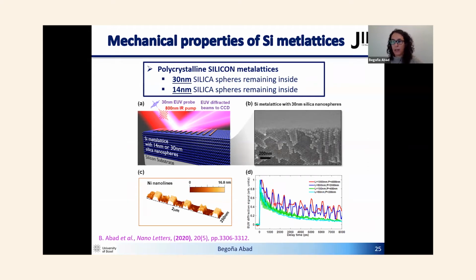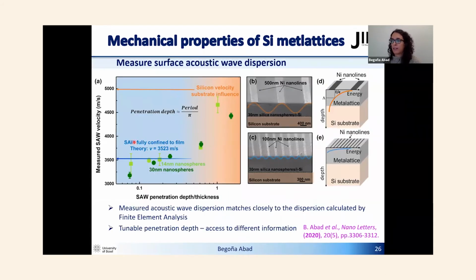Okay, so in the same measurement as I showed before, we could analyze thermal transport, and of course we can also analyze the acoustic part, the mechanical properties. Again, we study the 30 nanometer silica sphere and also the 14 nanometer one. We do our pump-probe spectroscopy. This is an AFM image of our nanolines on top, and we see how they conform to the surface of our metalattice. And then we study the frequency of these acoustic waves. If we extract from the Fourier transform the frequency of these waves, we are able to calculate the velocity of these acoustic waves inside the metalattice. And here it is plotted. This is the measured surface acoustic wave velocity as a function of the penetration depth normalized by the thickness.